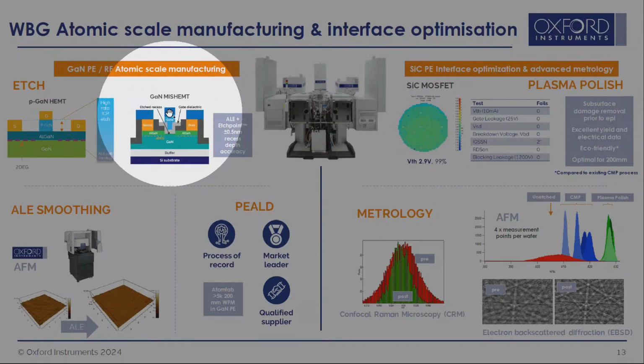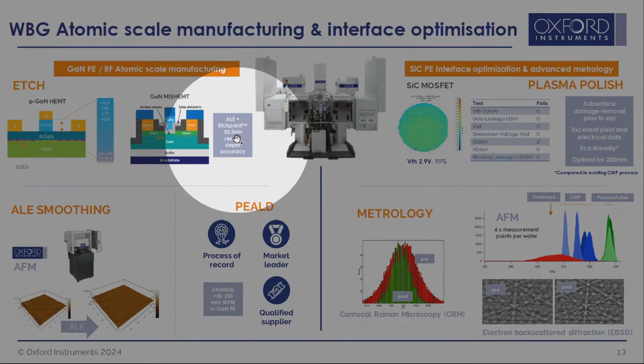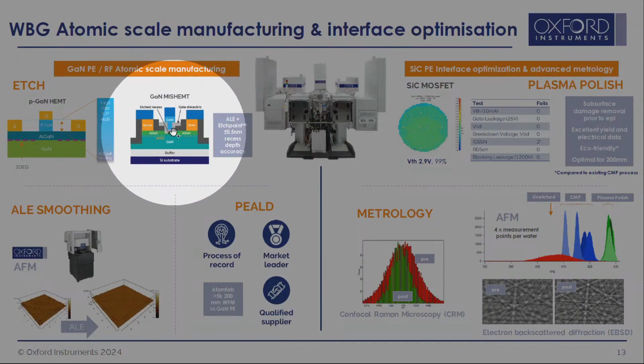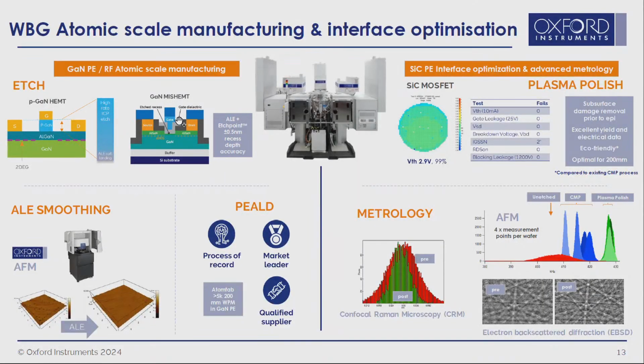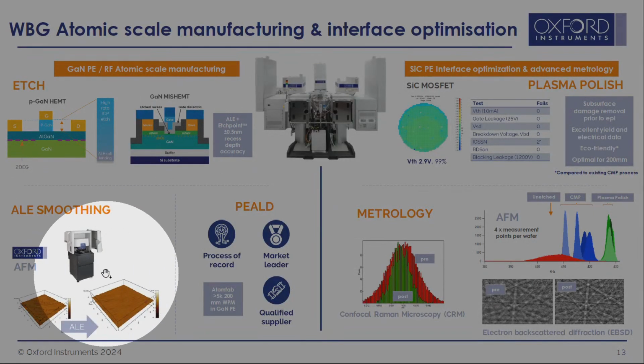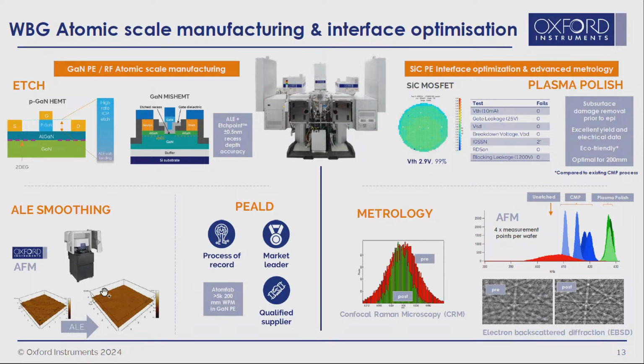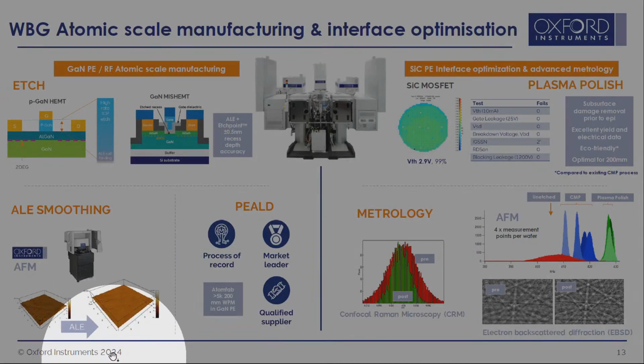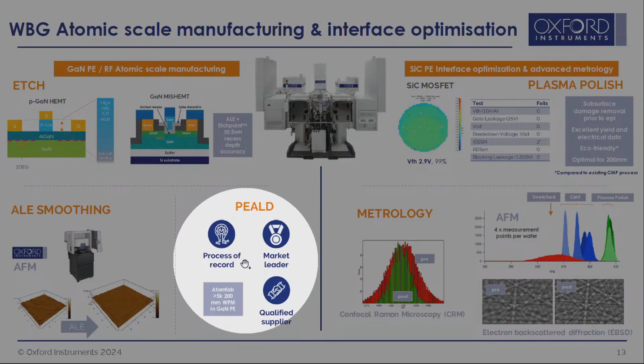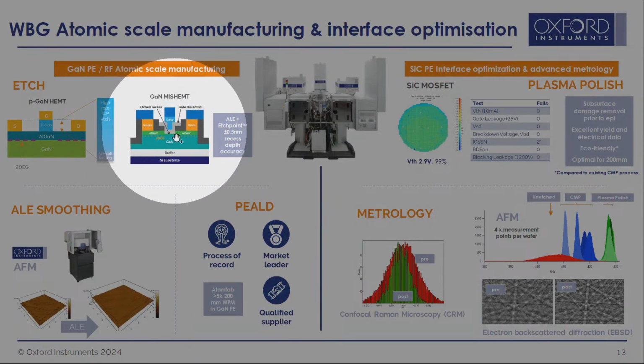So here, as I mentioned, in this recessed gate structure, we are etching a recessed gate structure of just 20 nanometers. And here, the control of the depth becomes very, very important when it's just a 20 nanometer etch. And as well, when we're doing that etch, we need to make sure that the surface roughness and the surface quality is as high as possible. And there we are choosing atomic layer etch to get both this control and also to get a very smooth surface. And then once we've done that etch, using plasma atomic layer deposition to put a passivation layer down.